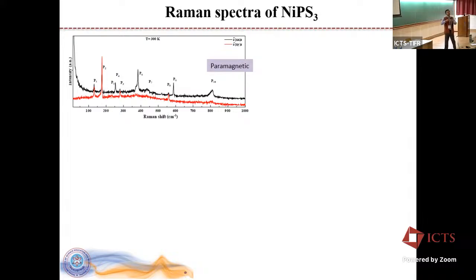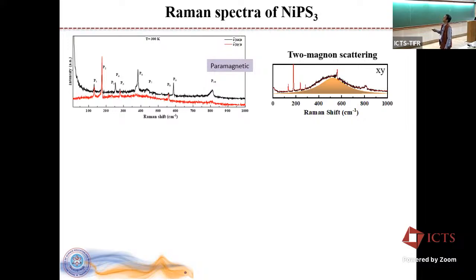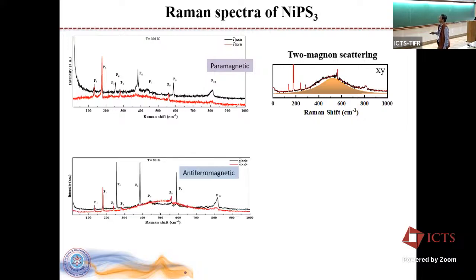Now, as we go to higher and higher temperature, this magnon gets almost quenched. But he wanted to dig a little more into that. What he saw was that at room temperature there is also some signal from the 2-magnon, which is not something one should neglect. He did not neglect it, which is why I think we have a story now. This is the 2-magnon at low temperature, and the NTU group, Chia-Sheung's group, also discussed that they could see this 2-magnon up to about 290 Kelvin. This is a very important point to be noted: anything related to magnon that is present above the Néel temperature is interesting.